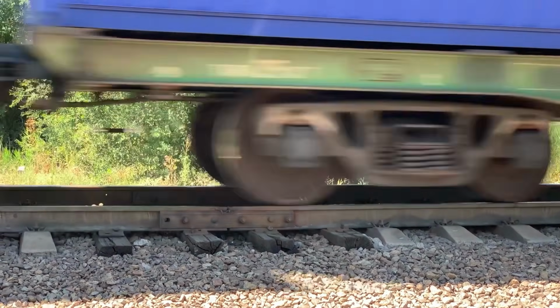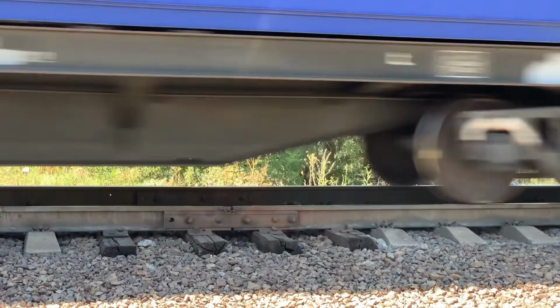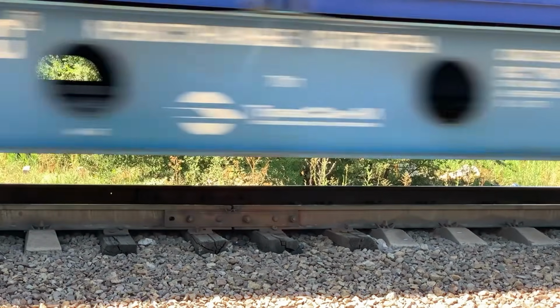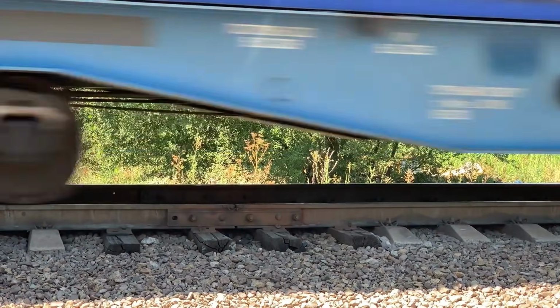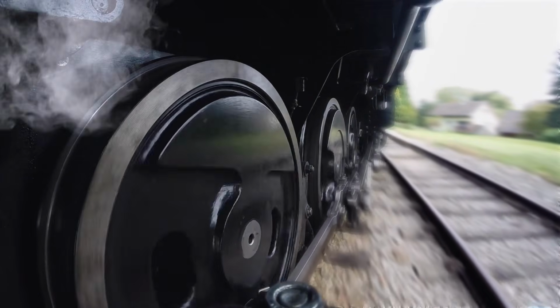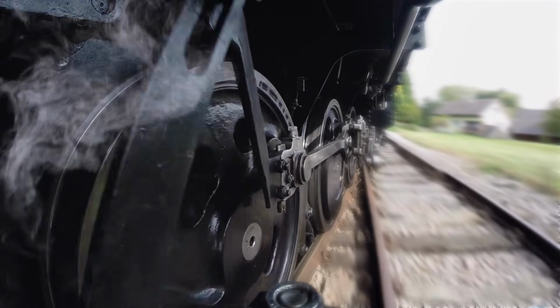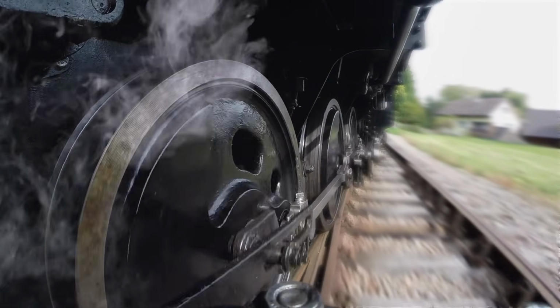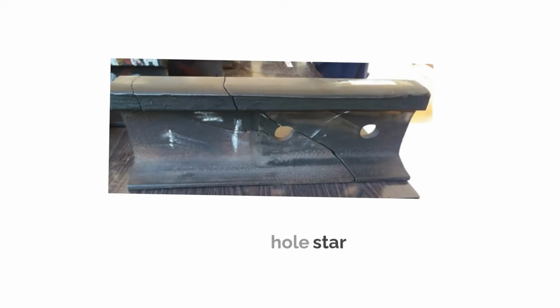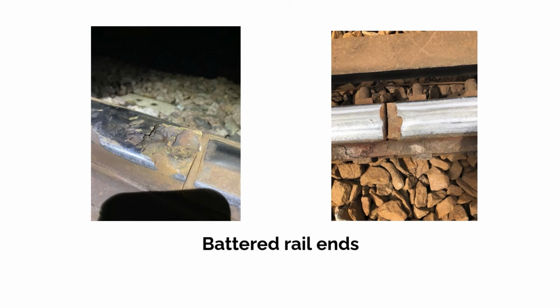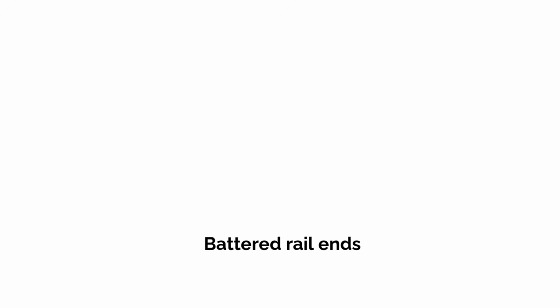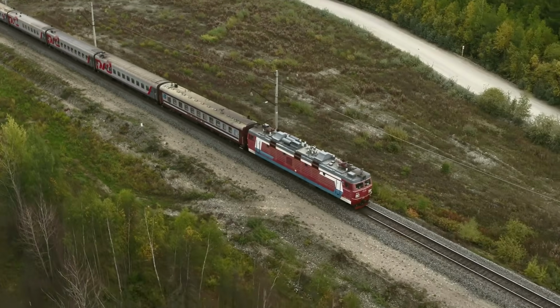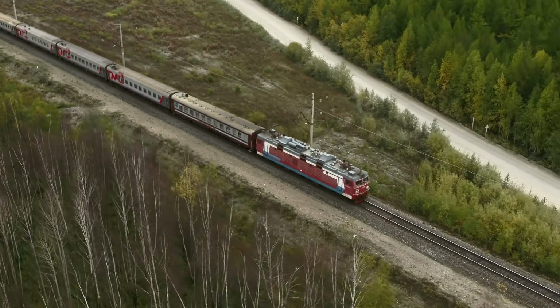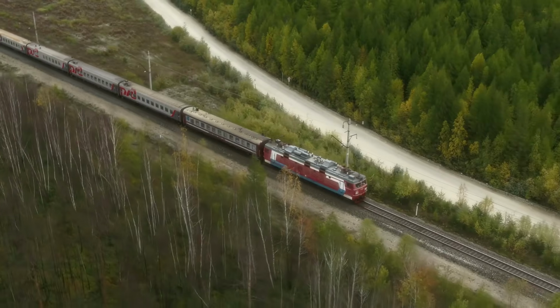It is, however, made worse if there is a lack of support either side of the joint. This leads to the joint itself flexing increasingly under each passing train. This in turn leads to increased loading and fatigue within the rail and the fish plates that form the joint. What failures do we see at joints? Cracked or broken fish plates, star cracking from bolt holes, and battered rail ends. A battered rail end is caused by repeated impact on the end of the rails at the joint. Both welds and joints look to achieve the same thing, the joining of rails, but each brings its own risks and its own failure mode.